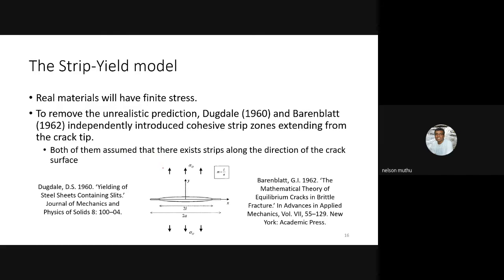So now Irwin saw the things from one perspective. Essentially, the idea was that if you could do a plastic zone correction factor for the crack embedded in elastic perfectly plastic material, we can be in a position to use LEFM principles. In the first instance, he equated the stress to the yield stress and found the value of lambda, but the equilibrium condition was not getting satisfied. Therefore, we had to do the second order estimate, and he obtained the value of rp. Once he obtained rp, he found that rp is nothing but 2 lambda.